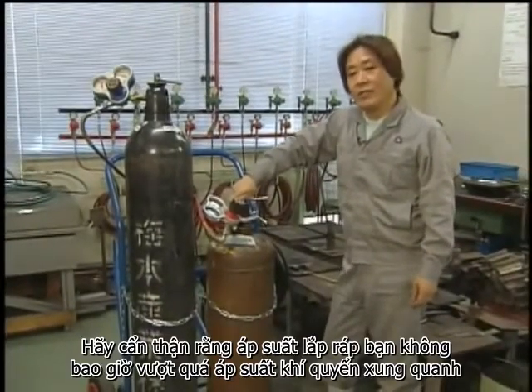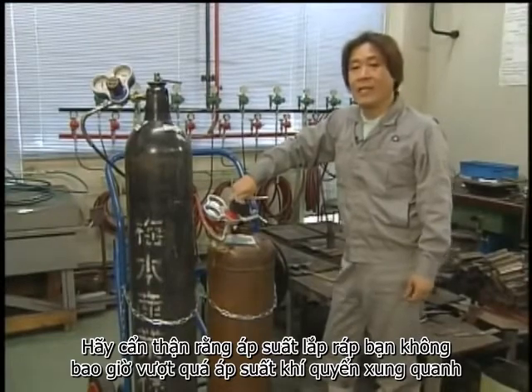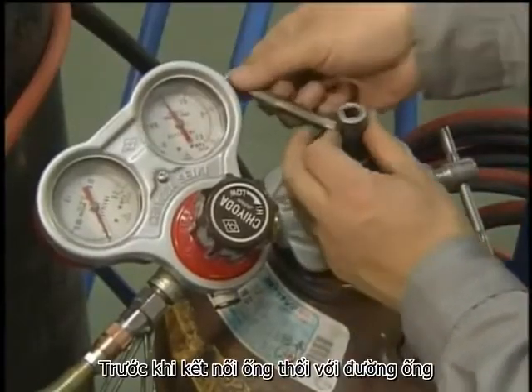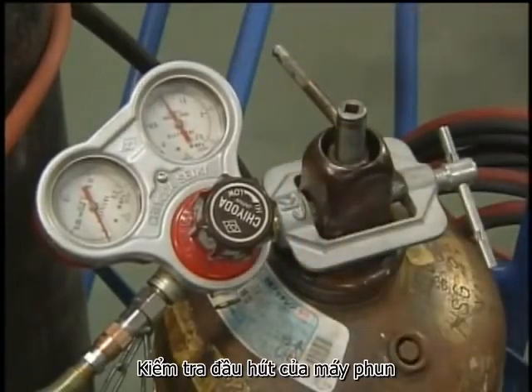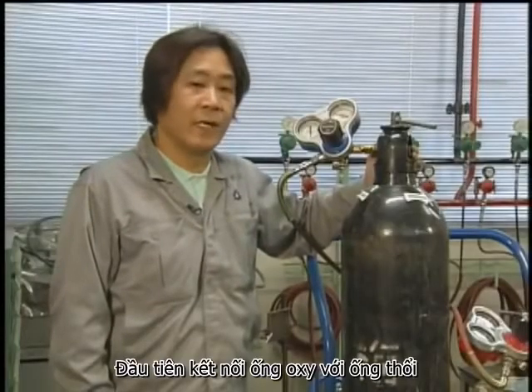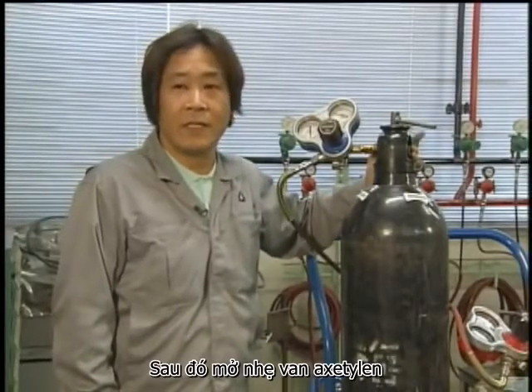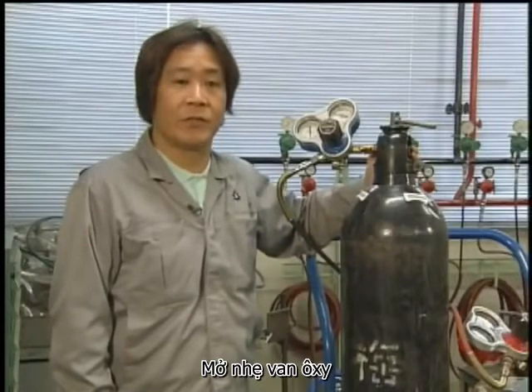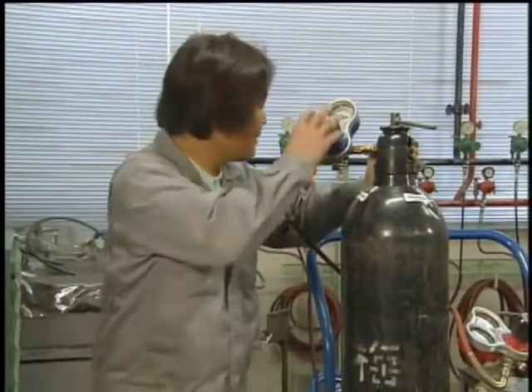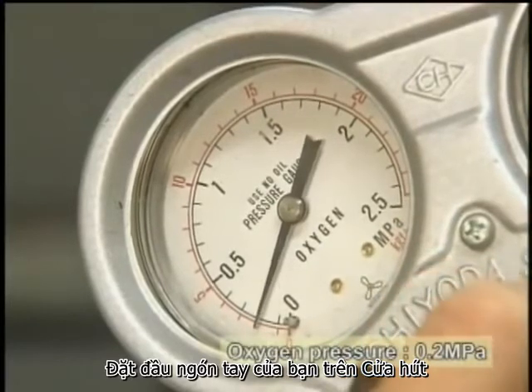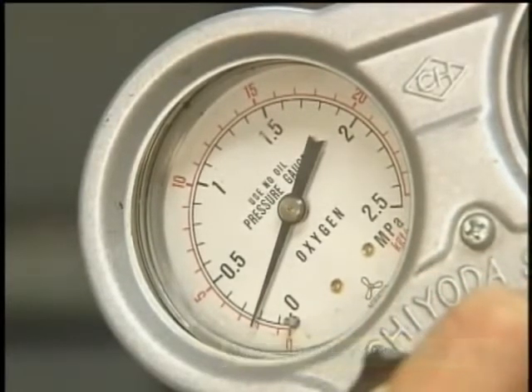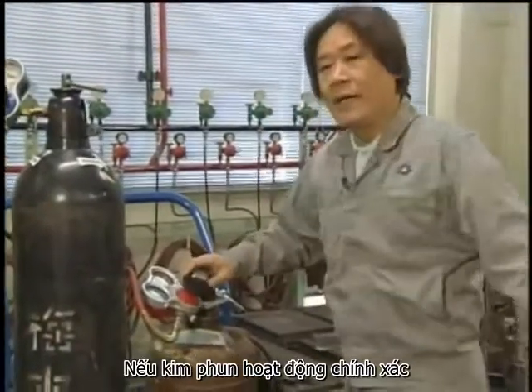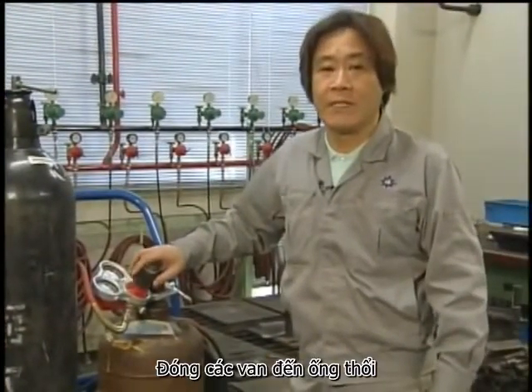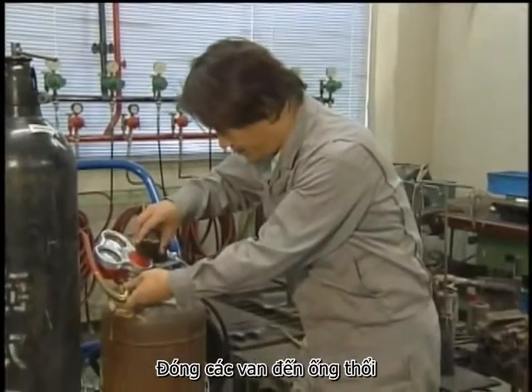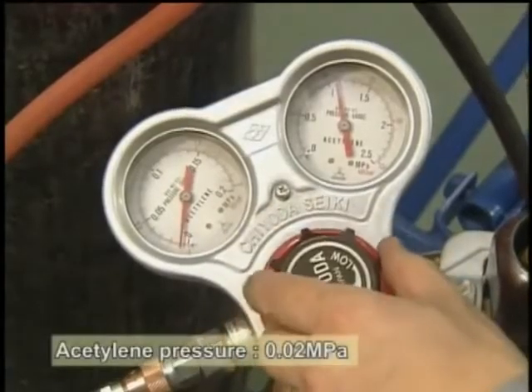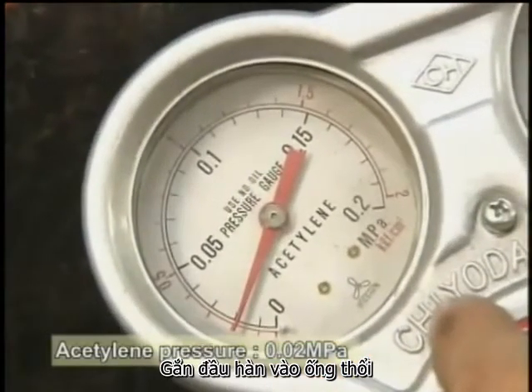The pressure inside the acetylene cylinder is low, so give the valve a half turn or single turn. The pressure used is determined by the thickness of the material used. In this case, you are using 2 mm thick mild steel plate, so the oxygen pressure should be 0.2 megapascals. The acetylene should always be at 1/10 of the oxygen's pressure, which in this case is 0.02 megapascals. Be careful that the acetylene pressure never exceeds ambient atmospheric pressure.